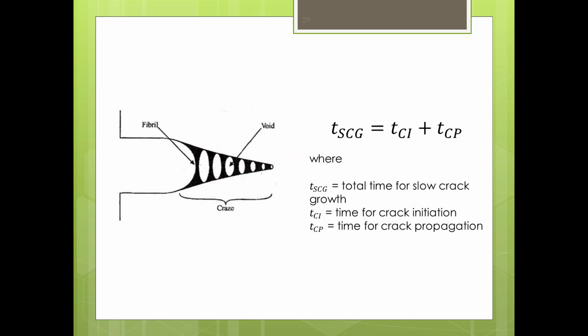For virgin plastics and virgin resins, there's a test out there called the notched constant ligament stress test, NCLS test. And it's basically where they take a notch into the sample, they pre-crack the dogbone sample, and they pull on it for a period of time in a Igepal bath to see how long it takes for that crack to propagate and pass through the entire sample. And that's really used as a control measure to make sure that the HDPE resins being used have enough stress crack resistance when placed in the field at higher levels of stress. The problem with the notched test is that it doesn't address the crack initiation phase of stress cracking.